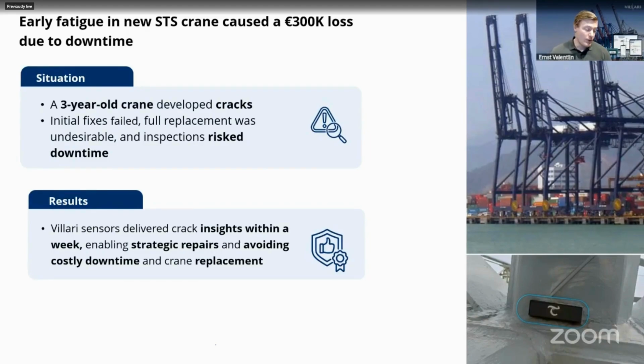was applied to both the repaired members but also to the areas around it to see if anything new is going to start happening here. In this case, which even for us is slightly unlikely, within a week we were already seeing some very strong signs of crack growth occurring. We flagged this to the customer, but also with a message: we're seeing crack growth, but we're seeing it very rapidly and at very short intervals.